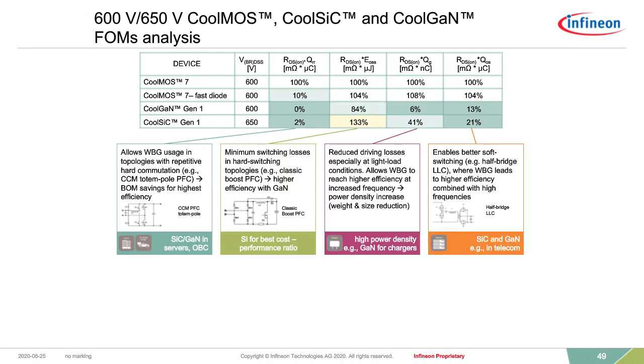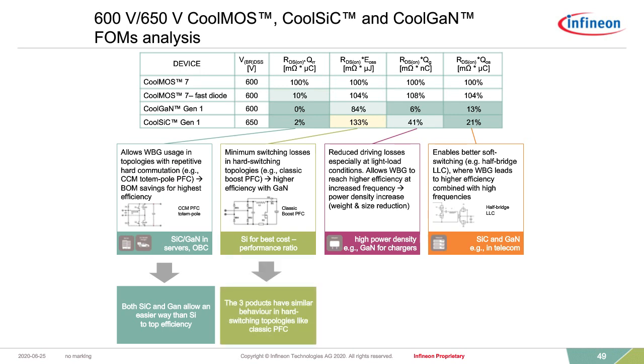Now, looking a bit more into detail at the individual figures of merit and how we use these figures of merit to position the individual technologies. Reverse recovery charge: very clear advantage, both for silicon carbide and for gallium nitride over superjunction. The body diode of superjunction can only be used in hard commutation in abnormal conditions, for a few cycles. It can never be used in constant operation. That is the domain where both silicon carbide and gallium nitride clearly have an advantage. Next topic, the energy stored in the output capacitance. As mentioned, superjunction is on par here with gallium nitride, and we believe that in that domain, superjunction will prevail in the market and will stay there. That is valid for topologies like the Vienna rectifier, like the classic boost, like topologies such as the interleaved two-transistor forward.